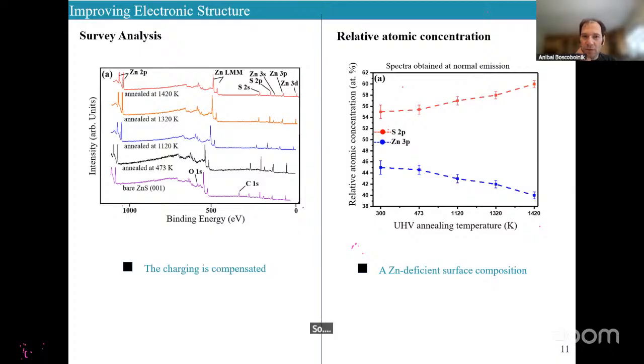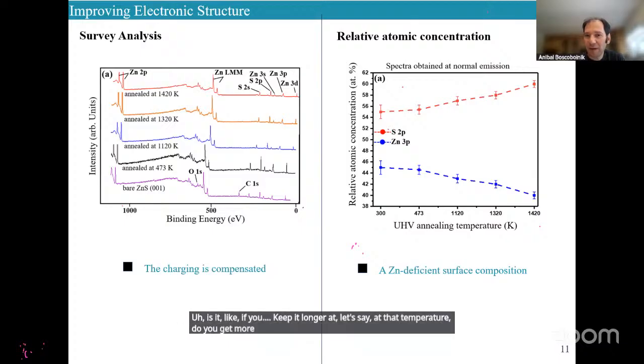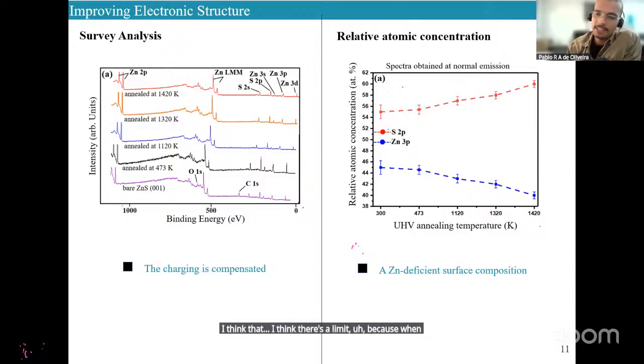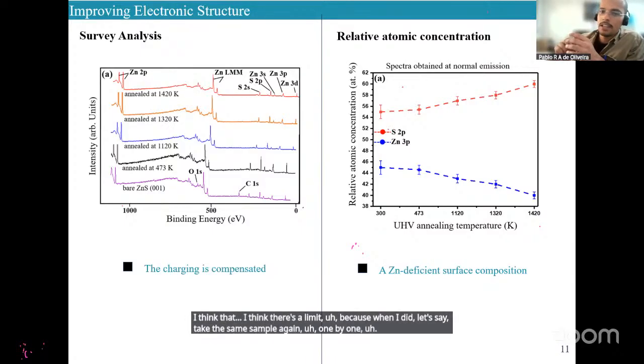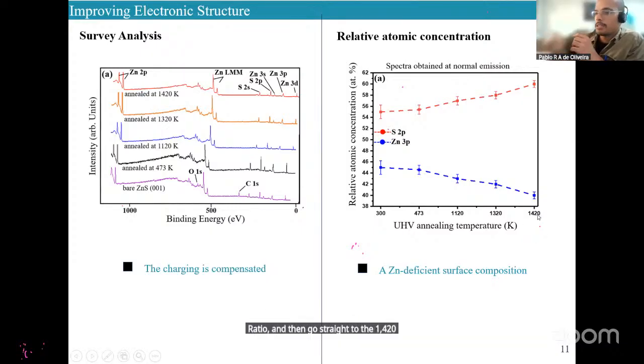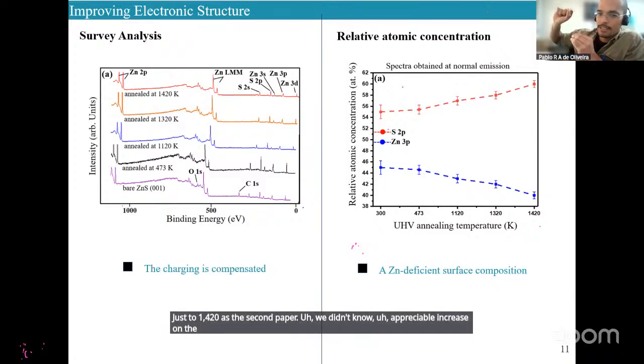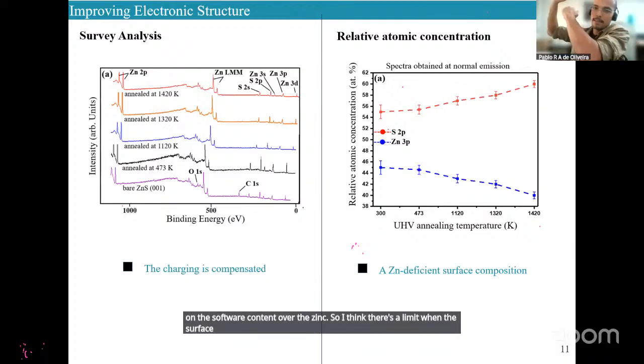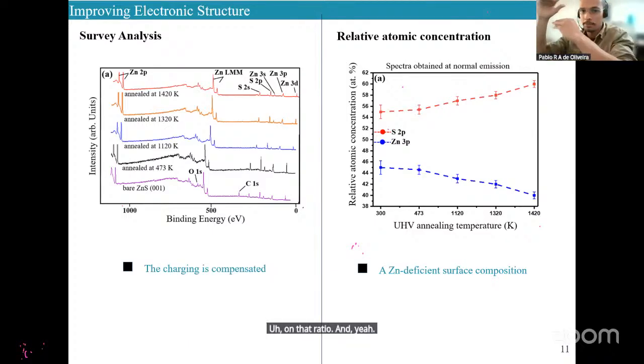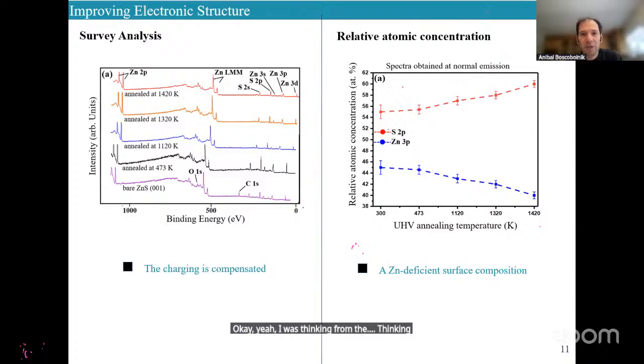So do you think you can tune the number of defects experimentally? You were showing us a function of annealing temperature in this plot here. If you keep it longer at that temperature, do you get more defects, or do you reach a stable amount of defects at each temperature? I think there's a limit, because when I took the same sample again, one by one, went straight to 1420 Kelvin, and then increased a little bit more, we didn't see an appreciable increase in the sulfur content over the zinc. So I think there's a limit when the surface defect gets stabilized at that ratio, and there's a threshold in temperature, I guess.